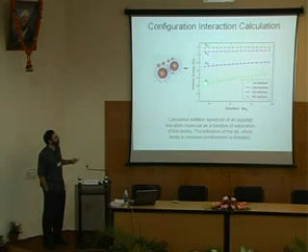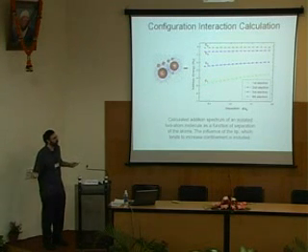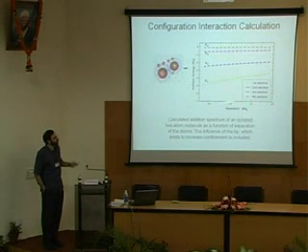This is the binding energy of the 4 electrons that will go. It turns out 4 electrons will go on there. And it's as a function of distance between the two donors. So donor number 1, donor number 2 are separated by distance d. They will hold up to 4 electrons. And our experiment, by the way, had an average separation right about here.